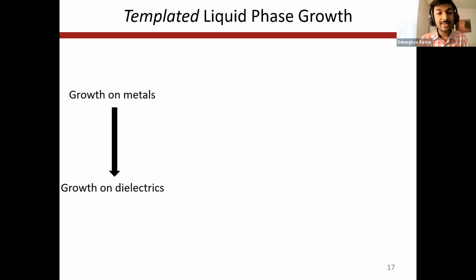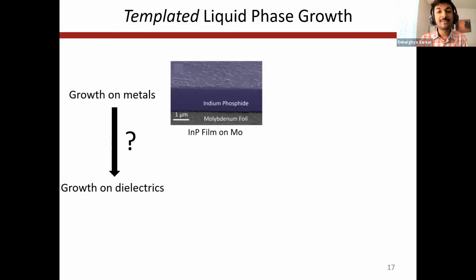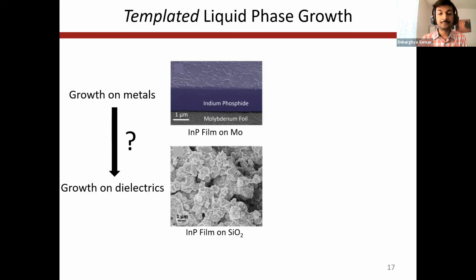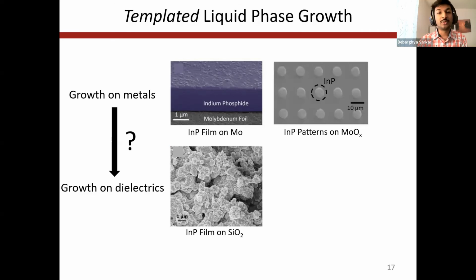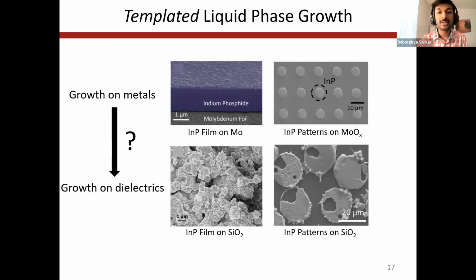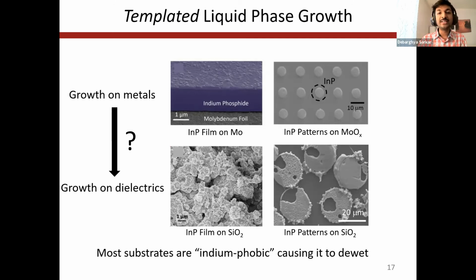Now, before we move forward, it's important to take a step back and recognize that the translation from the growth on metals, which was previously demonstrated, to the growth on dielectrics, which was demonstrated in my PhD, is actually non-trivial. What I mean by that is, compared to this flat and nice film of indium phosphide growing on metallic molybdenum foil, when similarly tried to be done so on dielectric silicon oxide, the morphology is not maintained. When patterned on metallic molybdenum oxide, the shapes are retained as intended, but form holes when similarly tried on dielectric silicon oxide. The reason is that most of these dielectrics are indium phobic, causing indium to de-wet, reducing the surface area of contact when it is molten.